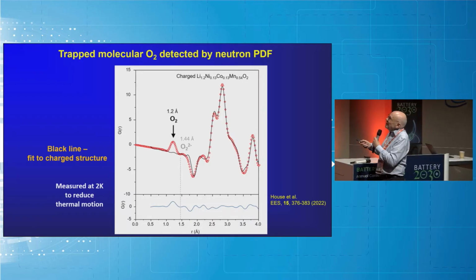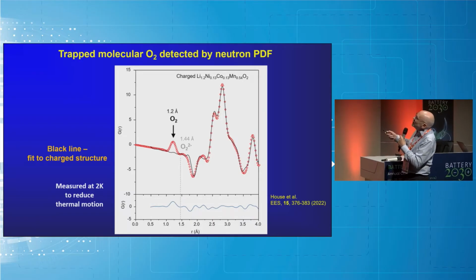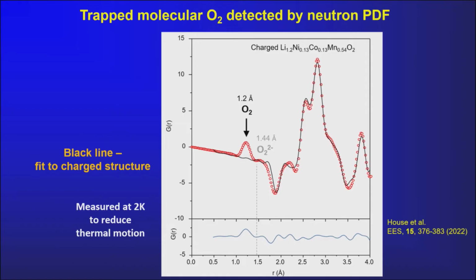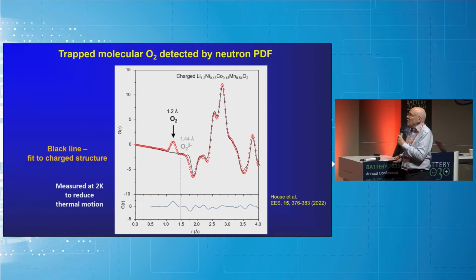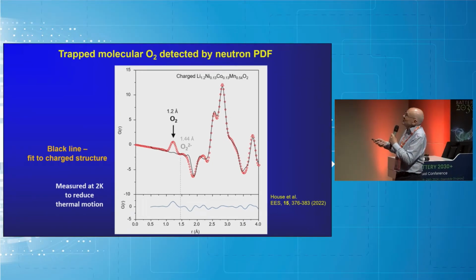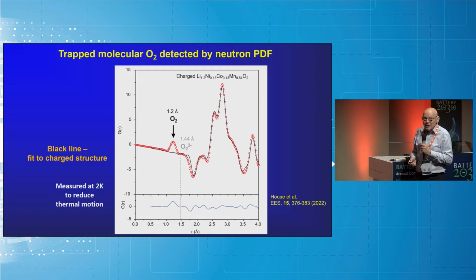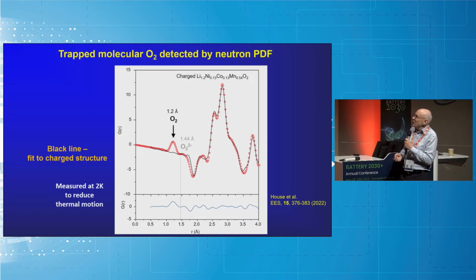The red dots are the experimental PDF pattern. The black is the fit to the charged structure. And this peak here that you see, that's not, of course, included in the calculation of the charged structure, this peak is exactly at 1.2 angstroms. That is the bond length of molecular oxygen. It is not the bond length of any other oxidized oxygen species. It's the bond length of molecular oxygen. So that's another completely separate technique indicating the presence of molecular oxygen in these charged materials.